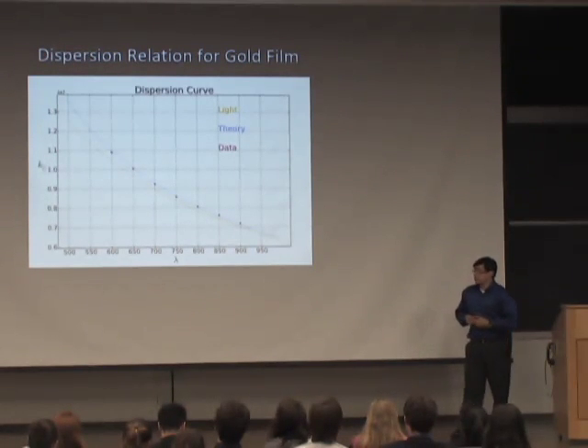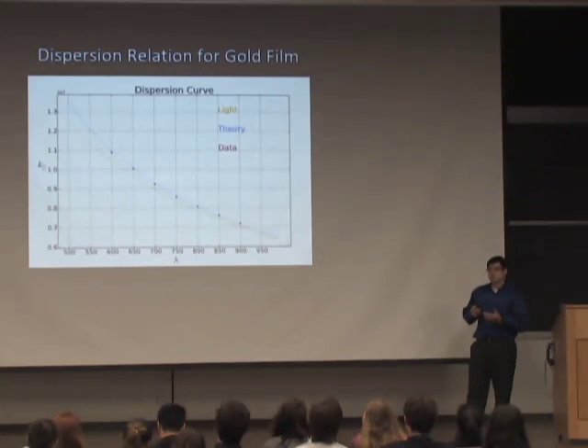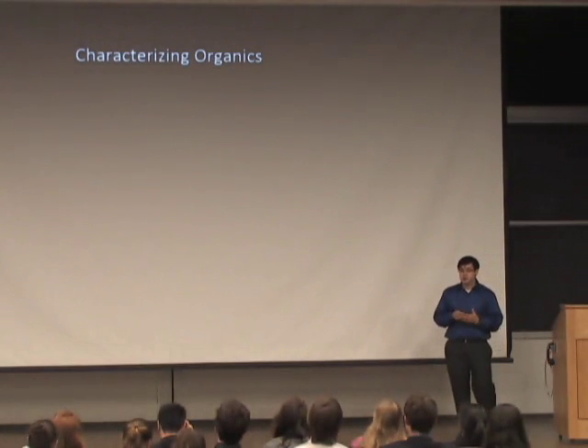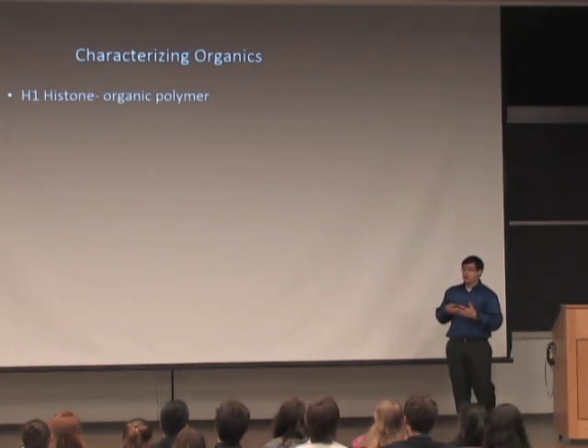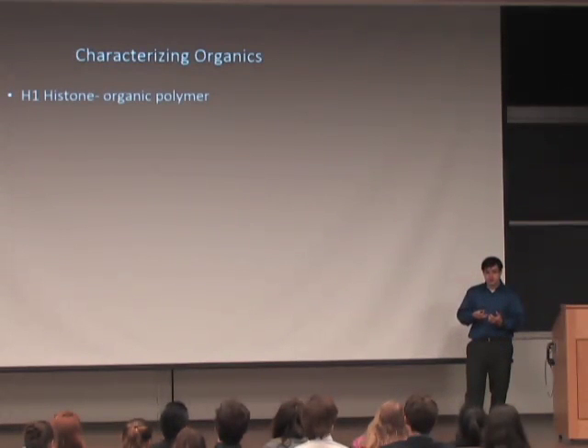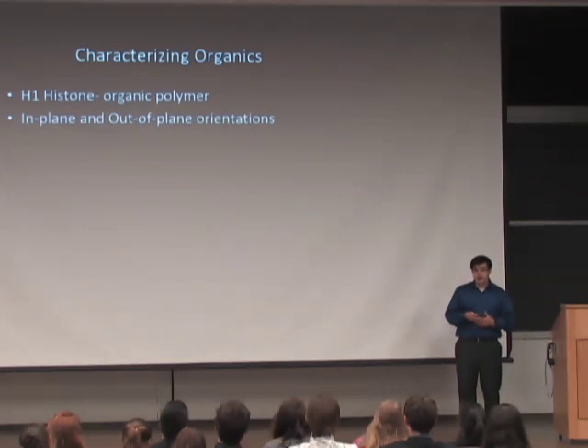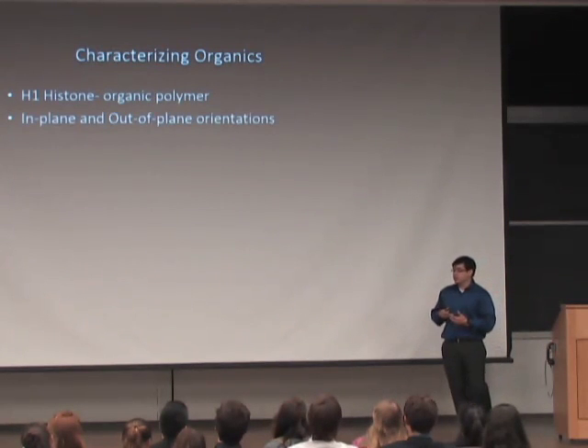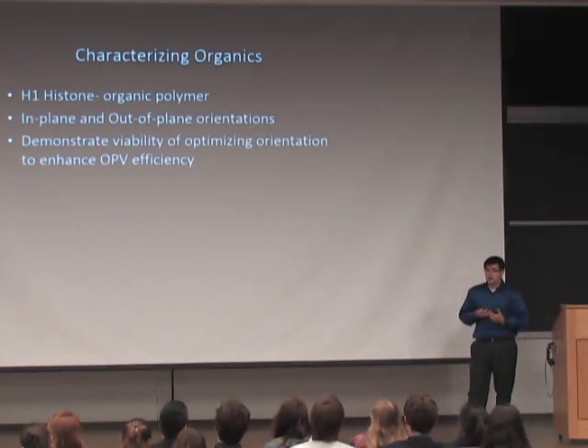So now with our gold film characterized, we can move into organics, and what we want to do is use H1 histone, some organic polymer, which demonstrates this varying orientation. And we want to use in-plane and out-of-plane orientations to demonstrate the viability of optimizing orientations to enhance efficiency.